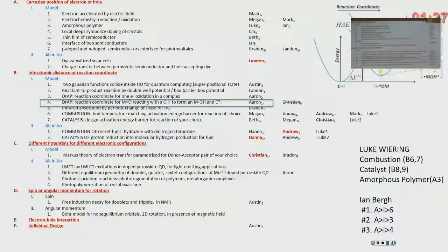And the rate of the hole transfer, which is as important as electron transfer, does depend on whether it is physisorbed, so through vacuum connection, or there is a little CH3OH group, a group similar to methyl. So a hydrogen bond. Yes, and then through the bond, the transfer is expected to be 1,000 times more efficient.